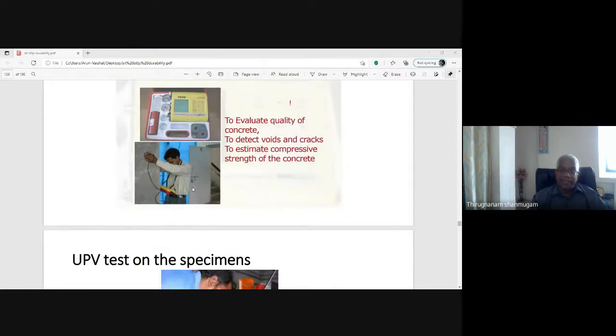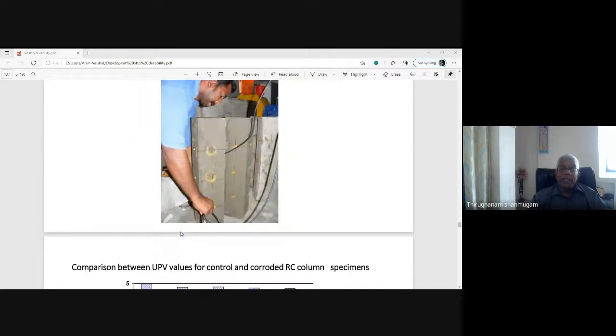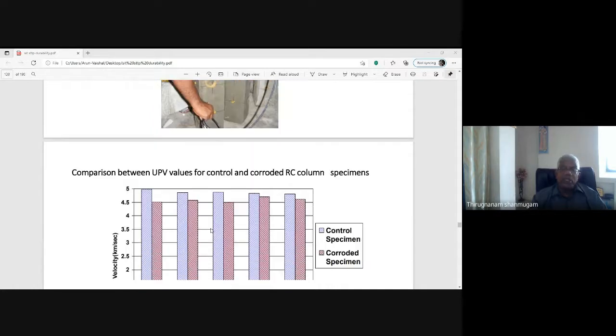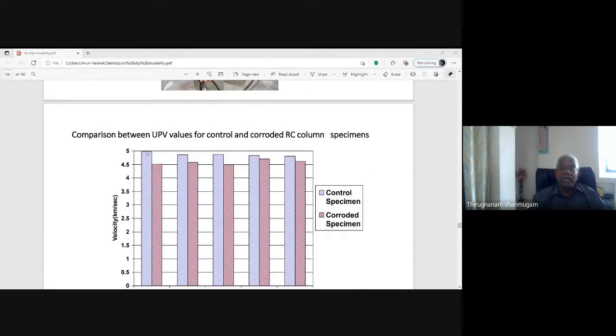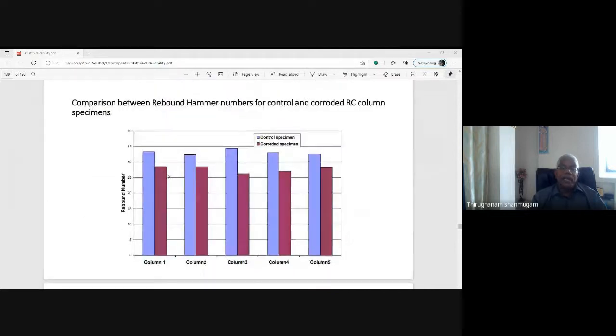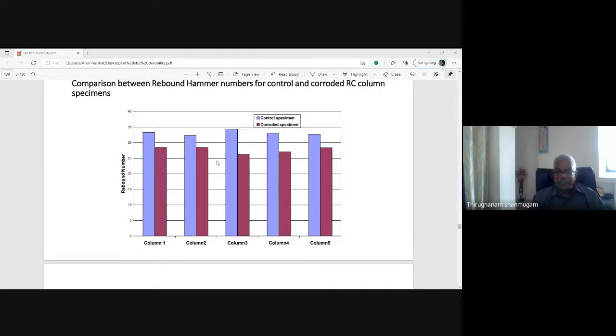Ultrasonic pulse velocity test. The voids and density, the imperviousness of the concrete are estimated, and the strength of the concrete is estimated. Both the corroded specimen as well as the uncorroded specimen indicate more or less the same velocity. The rebound hammer also shows the strength is not affected very much by the corrosion, only about 20% less strength is observed.